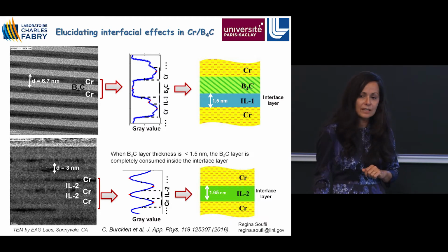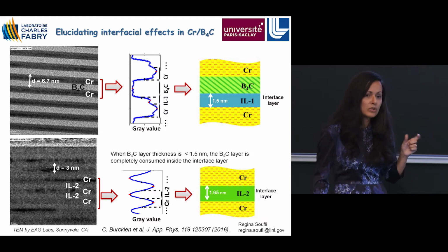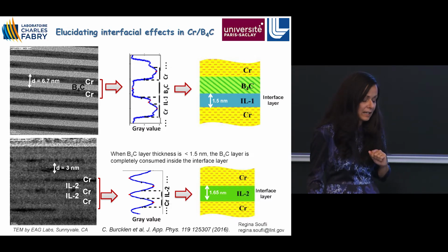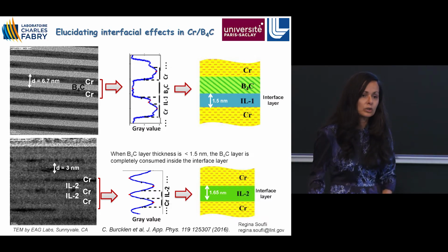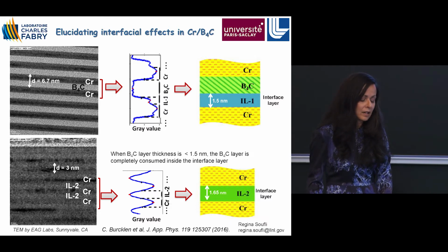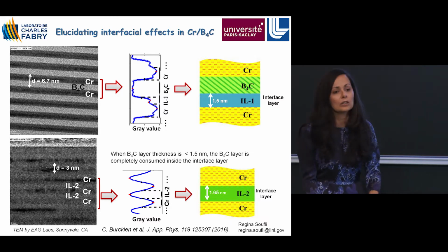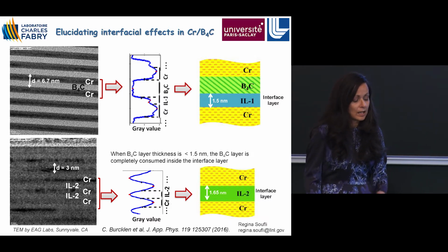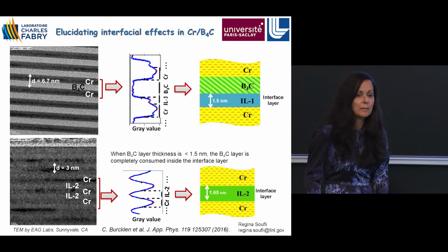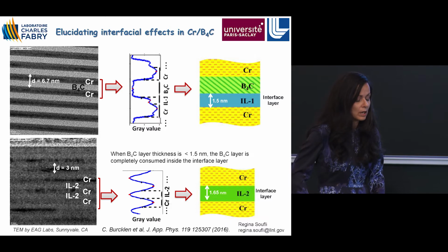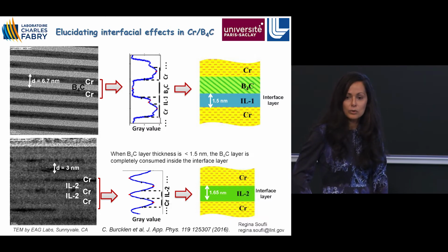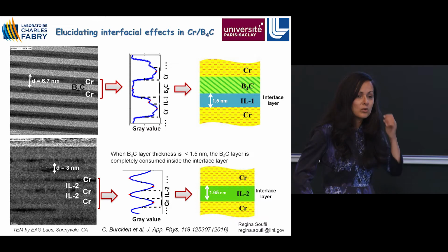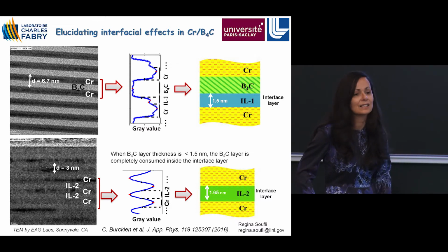We don't have conclusive evidence that there are compounds. We saw that there may be some oxygen compounds and nitrogen compounds with boron in the top layers, but again, this is the very top of the multi-layer. So there is definitely intermixing. We're not certain that there are compounds, and it's very likely that there may not be any compounds, but it's something that is very, very hard to determine. And especially after we saw the very good stability of this coating after 3 years, we were reassured. But it's something that we may continue to pursue in the future if we want to get to the bottom of this question. We haven't gotten 100%, but we tried.